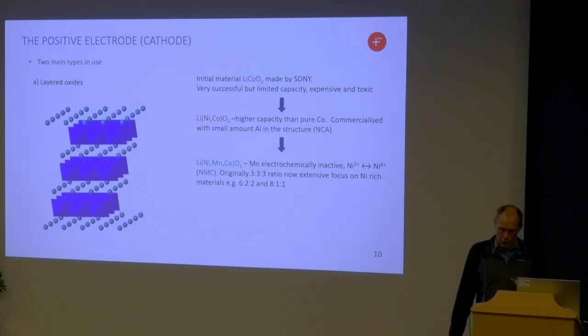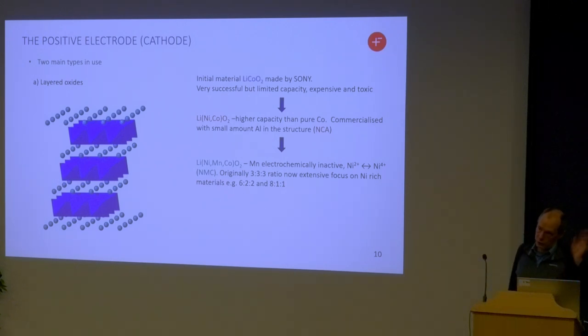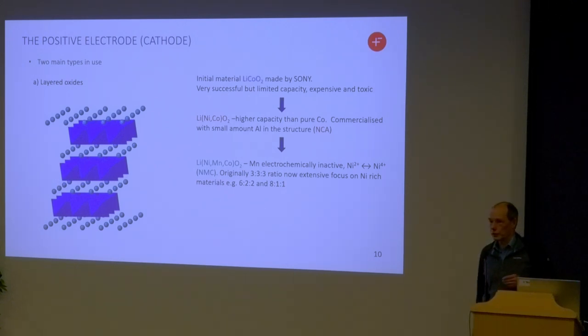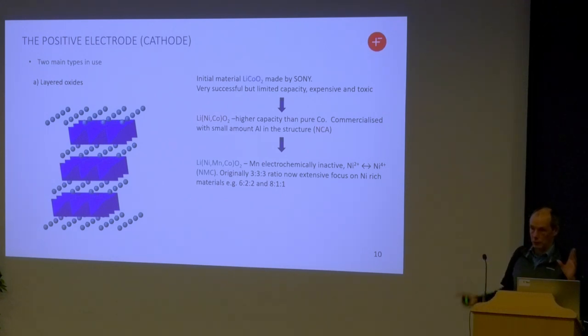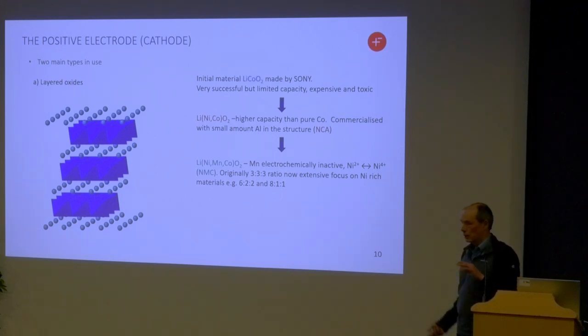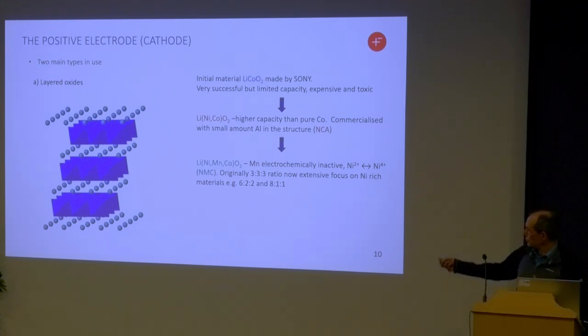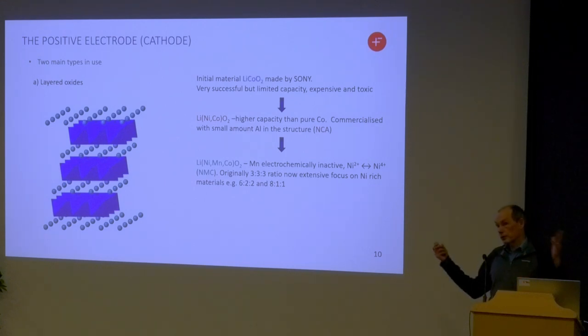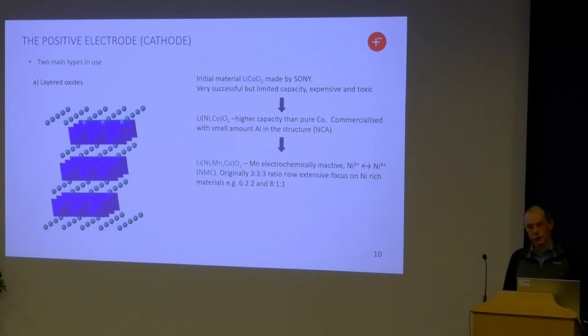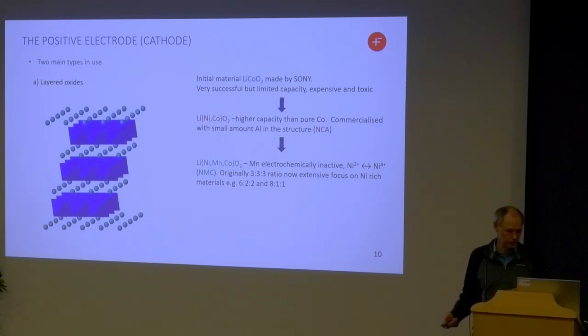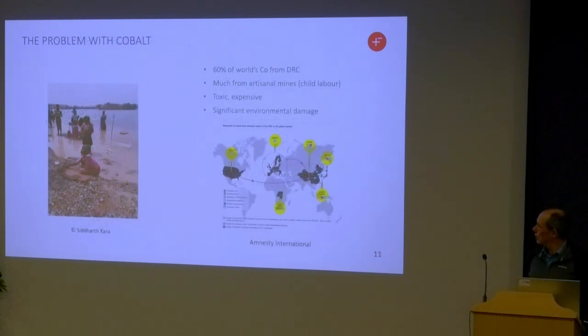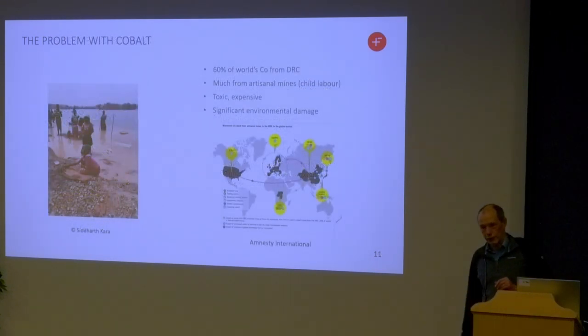So I mentioned milliamp hours per gram, I'm going to talk about them a lot. Lithium cobalt oxide has a practical capacity of 130 and an operating voltage just under 4 volts. NMC operating voltage is about the same, maybe actually slightly lower, 3.8, but you can get usable capacities of 180, 190. So that's the driving force to moving to NMC. This is the driving force for getting rid of cobalt.